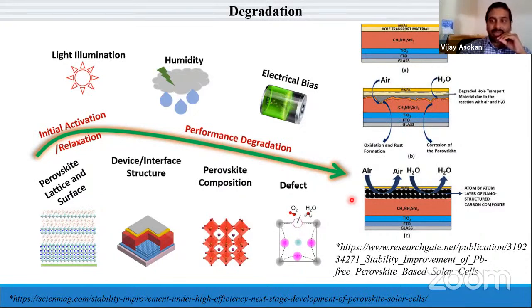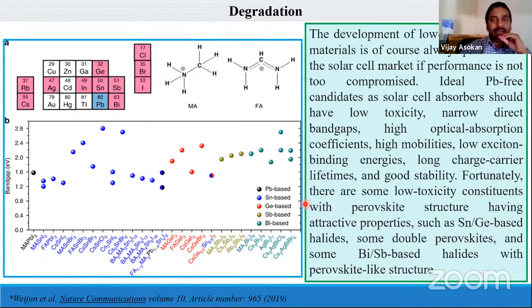So that can be replaced with either a two-dimensional material layer, nano carbon composites, or other nano combined materials. So it can avoid reaction with air and with water. Those things need to be considered when we are talking about perovskite solar cells. Many things have been developed, including the perovskite material layer, which I showed previously, using lead-based, tin-based, germanium-based, antimony or bismuth-based combinations of perovskite structure to avoid such degradation, improving lifetime and giving good stability.